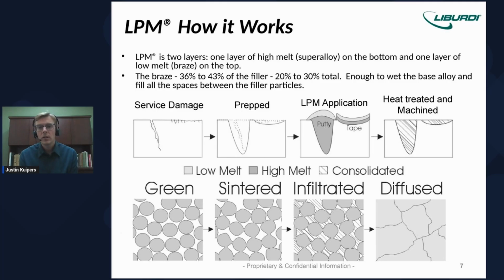The putty is generally used where we have irregular shapes, such as cracks. For example, we've removed a crack and we have a groove, and then we can use our putty to fill that groove that's been created. Or in contrast, where we want to do uniform buildups of thickness on a wall, we can use tapes.